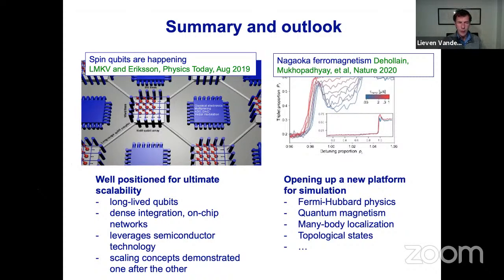To give you an idea, in gallium arsenide, typically we have an orbital energy spacing of about 1 milli-electron volt and charging energies of a few milli-electron volts. So it's actually not that far away from the regime that you're talking about. And yes, with a modified design, you can reach it. You can also reach it if you use a different semiconductor where the effective mass is different. That also, of course, changes your level spacing, keeping everything else the same. Or you can put more metal nearby and reduce your charging energy, etc.